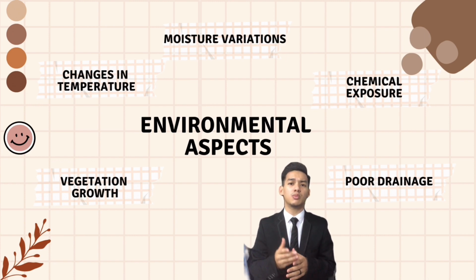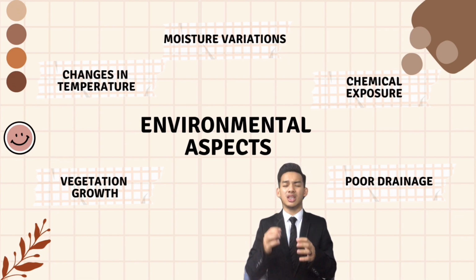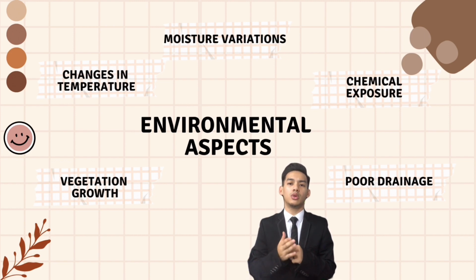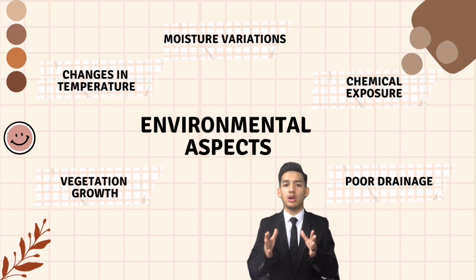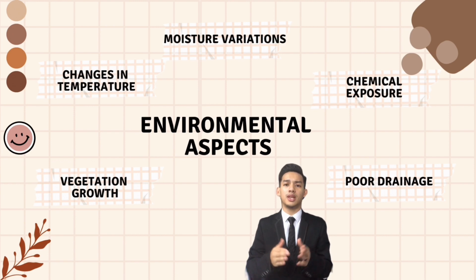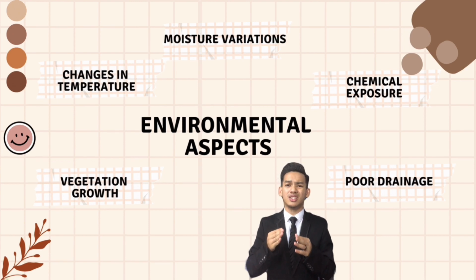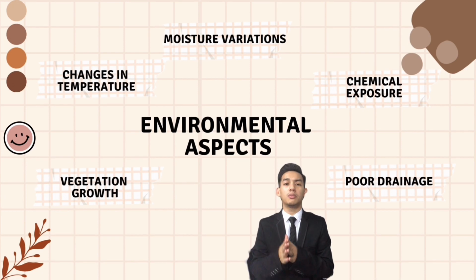Besides that, chemical exposure. Over time, concrete can degrade as a result of exposure to certain chemicals, such as de-icing salts, oil, or acidic substances. These substances may penetrate the slab surface, weakening it and increasing the likelihood of cracking. Other than that is poor drainage. The slab may settle unevenly and break as a result of the increased moisture content weakening the subgrade or promoting erosion. Then, vegetation growth. As neighboring trees or plants swell, their roots may put a strain on the slab. If the roots pierce the concrete, this pressure may cause the slab to move or break.